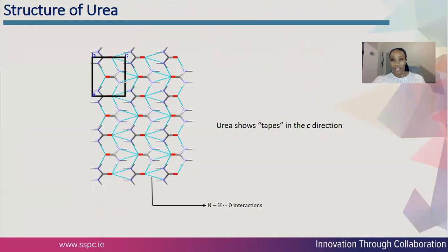Regardless of the quantitative accuracy, though, the mechanical behavior of a crystal can still be linked to structural features. A good archetypical model is urea. It features only a single type of intermolecular interaction, but it is not an active pharmaceutical ingredient. The crystal structure of urea is composed of planar molecules arranged in a head-to-tail fashion, or tapes, along the crystallographic C direction, as shown in the image here. The tapes are held together by a strong network of hydrogen bonds, and the network also extends in the orthogonal direction out of the screen.